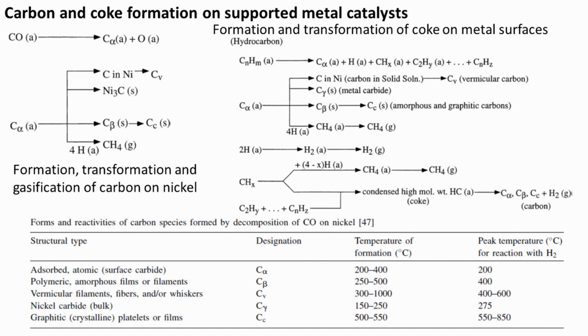It is not surprising that addition of a noble metal to base metals prevents carbon formation. For example, addition of platinum to nickel lowers the carbon deposition rate during methanation, while addition of copper to nickel substantially lowers carbon formation in steam reforming.